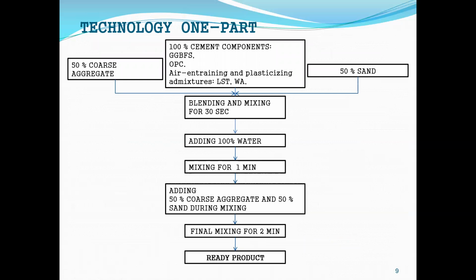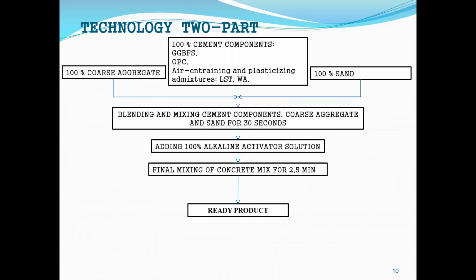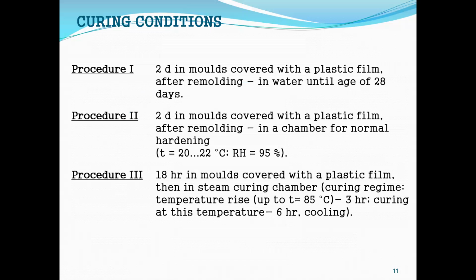Alkali-activated blast furnace cement concrete was prepared by one-part technology, when alkaline component was introduced in a concrete mixer in dry form, and two-part technology, when alkaline component was introduced in liquid form. The specimens hardened in water under normal conditions and under steam curing.